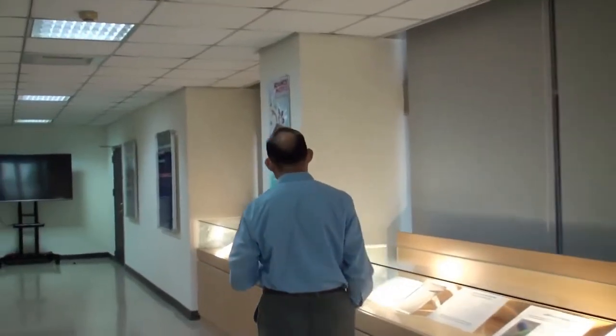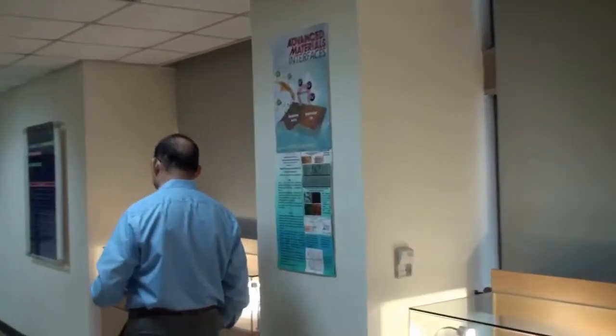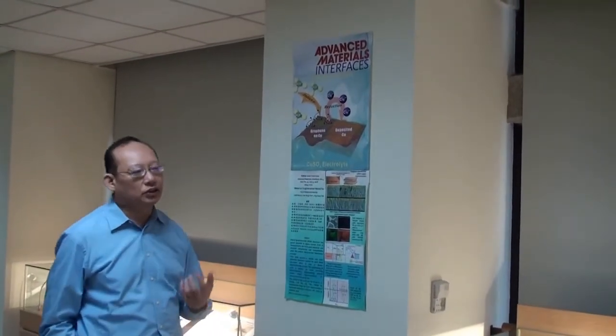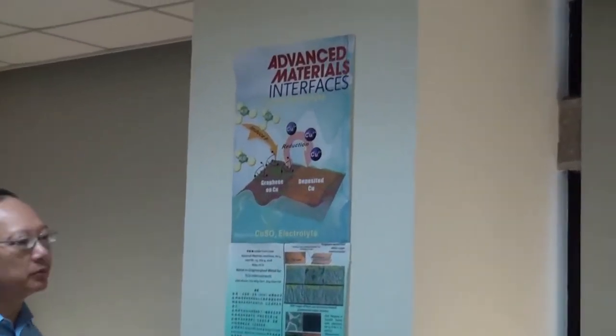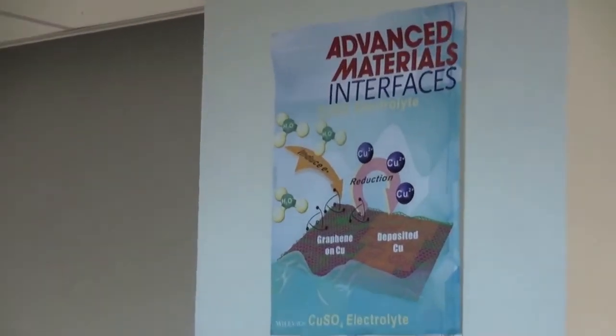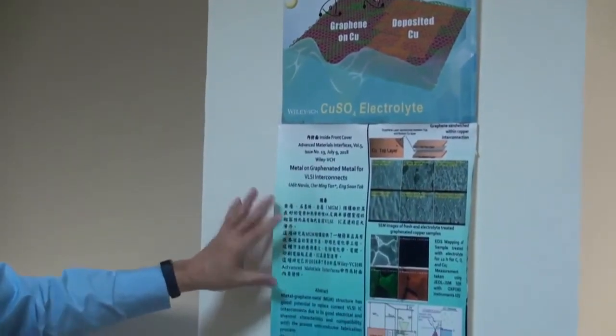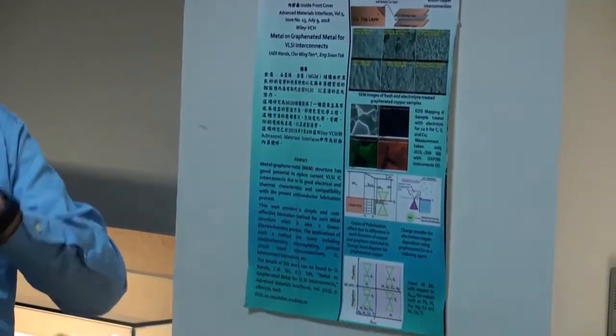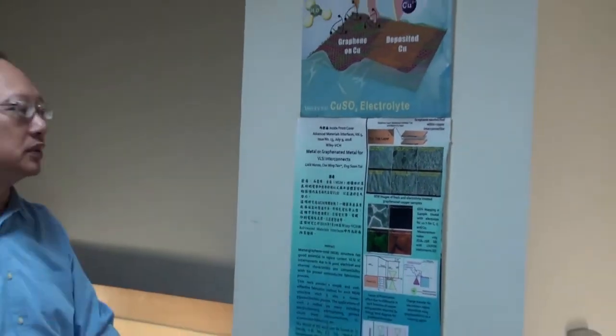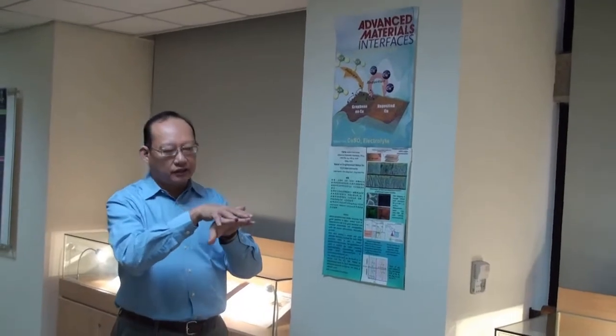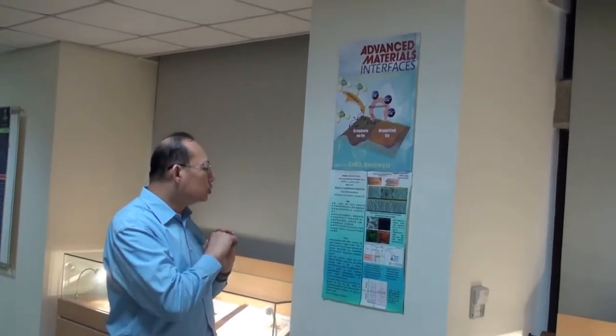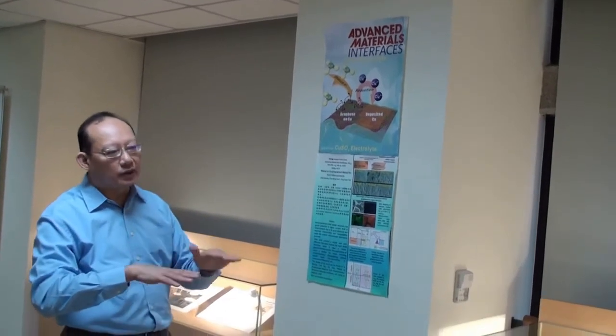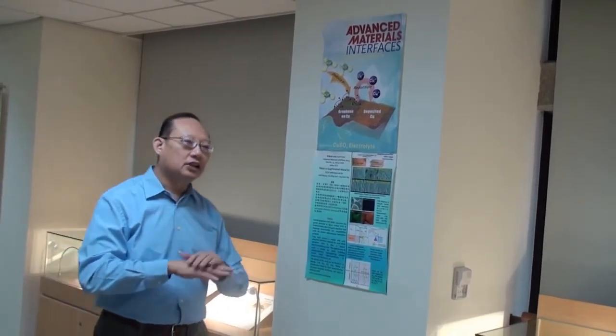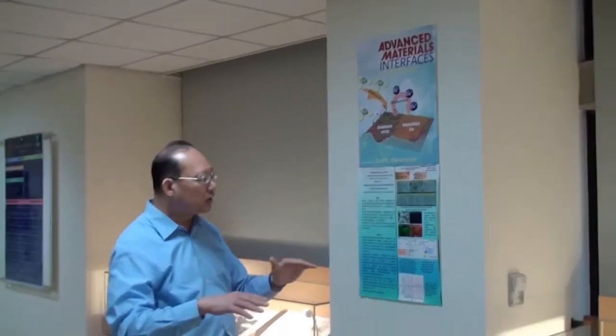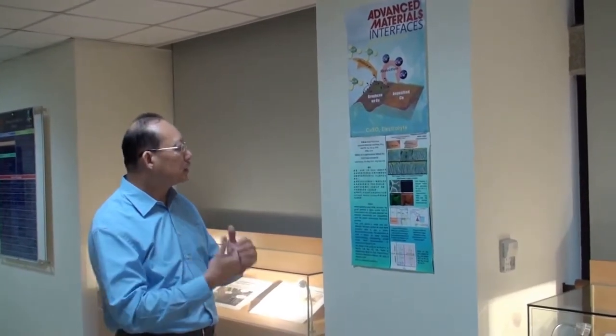I would also like to mention that interconnect is one of the main problems for IC, and copper interconnect is already running out of steam because of the high current density, electron migration and the heat. So what I've done is that I developed a new interconnect material, where I put metal, graphene, and metal. In other words, graphene is in between the copper. I developed a method to insert the graphene inside the copper. By so doing, most of the current will be carried by the graphene, because graphene has better conductivity than copper, and is also a very good heat dissipator. As a result, the electron migration improves.